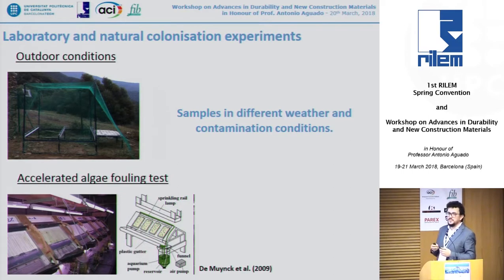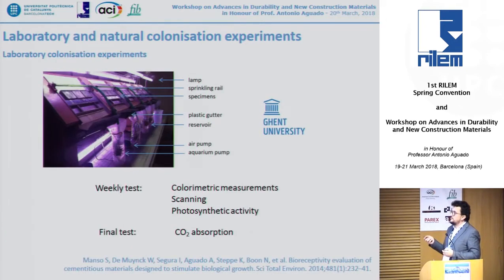So, after the development and the study on the dosages of this material, we prepared a very extensive laboratory and natural colonization experiments. We settled different samples both in natural exposure conditions and outdoor conditions, and also in the laboratory to make the accelerated algae fouling test developed by De Muynck et al. at Ghent University.